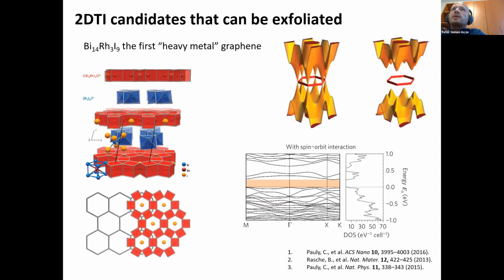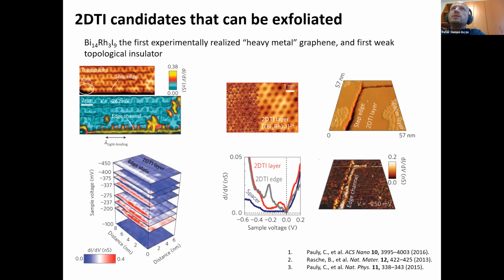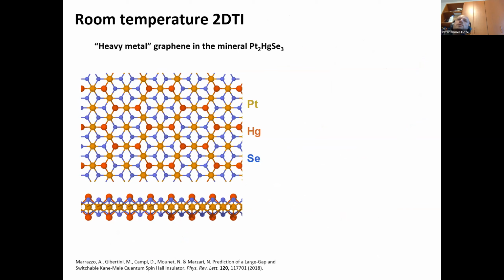And this has a band gap of around 200 millivolts, which is quite large. But based on experiments in our group, it is very hard to exfoliate this to the monolayer, possibly because of the ionic bonding between the layers in this material. But it has been shown by STM that it does indeed host edge states, and these edge states have been characterized quite well.